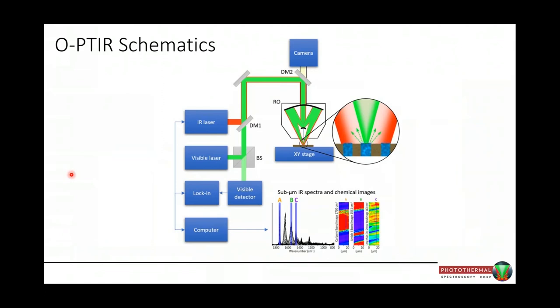This is another picture of the optical schematic. You have your pulsed tunable IR source that is combined with a visible laser source of a shorter wavelength, and they're both sent through the same Cassegrain objective onto a sample that sits on an XYZ stage. And you can see that the diffraction-limited spot size of the visible green laser is much smaller than the red infrared laser.